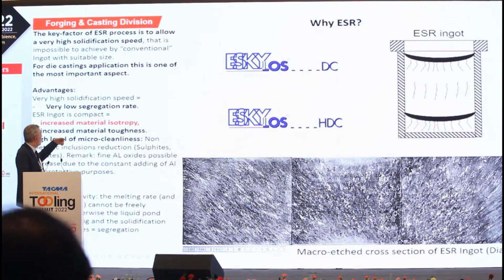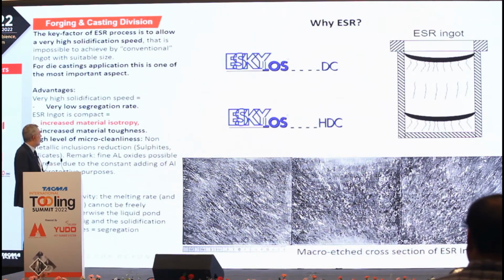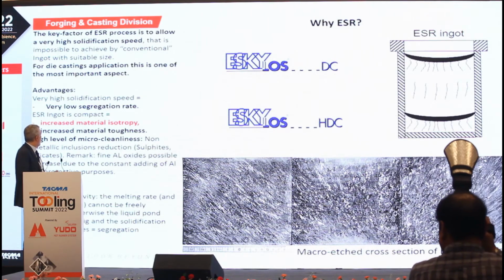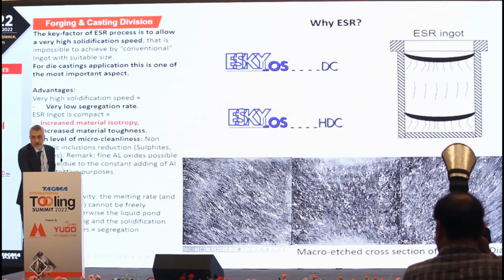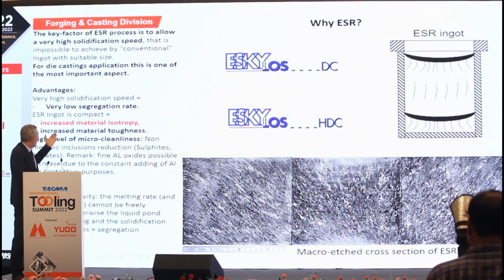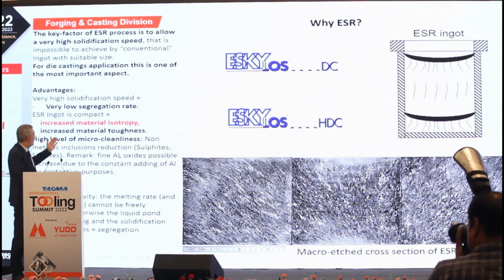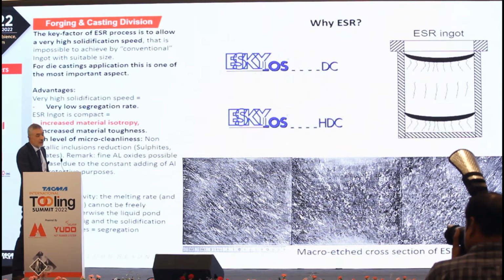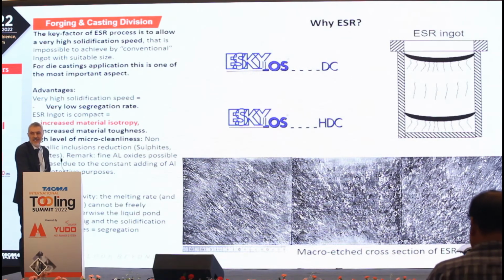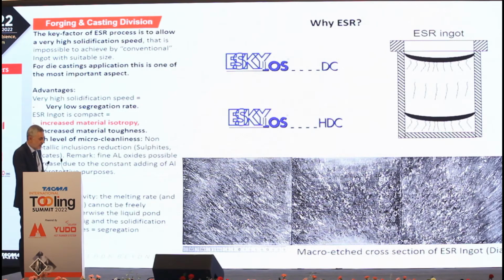Advantages: very high solidification speed, very low segregation rate. ESR ingot is compact. So by this way, we have an increased material isotropy, an increased material toughness, high level of micro-cleanliness, so non-metallic inclusion reduction. Of course, we have to accept some disadvantage, which is lower productivity. But if we want to produce quality steel, we have to accept this disadvantage.